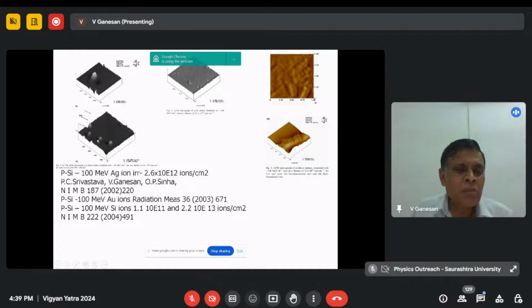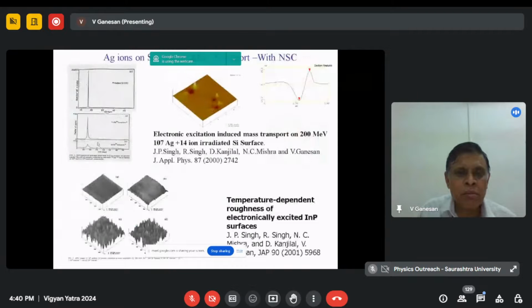Everywhere blisters are coming out, very random. It is not proportional to the number of ions that we see. It's about 10^12 ions per centimeter squared. We don't have that many blisters, but there are some collective effects. But it is a very huge effect, and every blister is surrounded by a small hole also. This made us make a very systematic study on that.